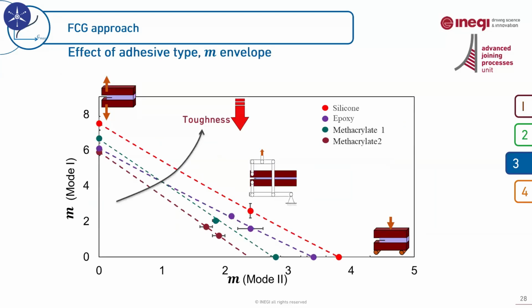We have also conducted this test under various mixed mode loading angles. And when we plot M envelope for different mode mixities, we find that despite the large difference in static behavior among the adhesives that we have tested, their fatigue crack growth behavior doesn't differ significantly. And the M value more or less remains within a relatively narrow range for all loading modes. But a general trend for all mode mixity is that in case you have a lower fracture energy under quasi-static, you should expect a higher M value under fatigue.